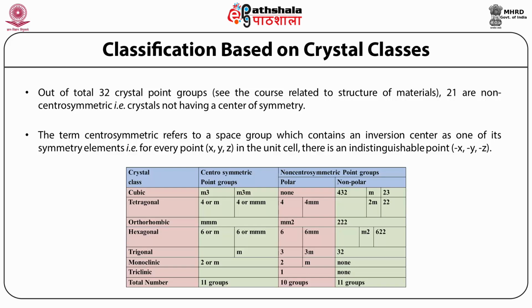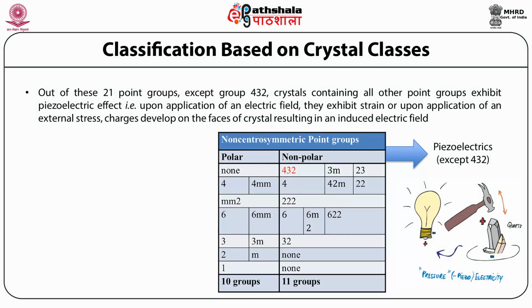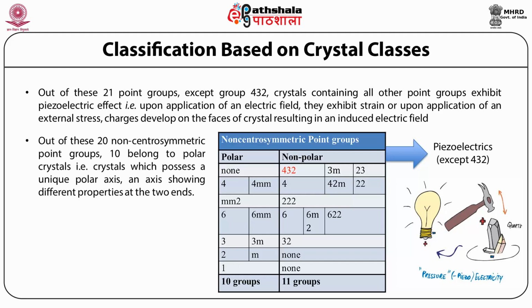The total number of centrosymmetric point groups is 11, non-centrosymmetric polar groups are 10 and non-polar are 11. Out of these 21 point groups, except group 432, crystals containing all other point groups exhibit the piezoelectric effect. That is, upon application of an electric field, they exhibit strain, or upon application of an external stress, charges develop on the faces of a crystal, resulting in an induced electric field. Out of these non-centrosymmetric point groups, 10 belong to polar crystals, that is, crystals which possess a unique polar axis, an axis showing different properties at the two ends.